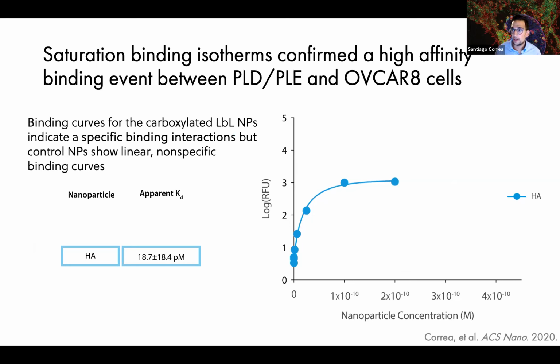And so this is where we expose cells at 4 degrees C to different concentrations of nanoparticles so that we can actually saturate the surface of the cell, since at that temperature the cell can't actually internalize any nanoparticles. This allows us to essentially obtain data that we can fit and extract useful parameters from, such as the apparent KD between the nanoparticle and these ovarian cancer cells.